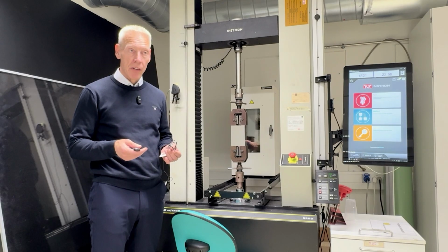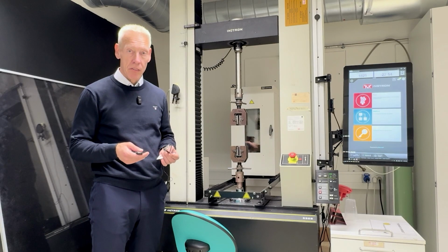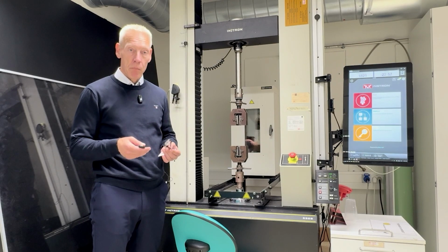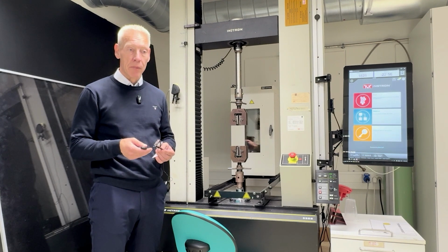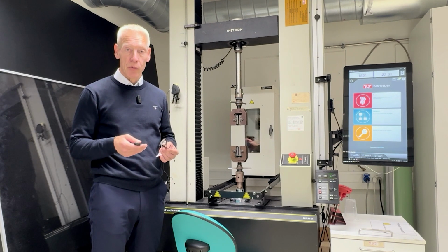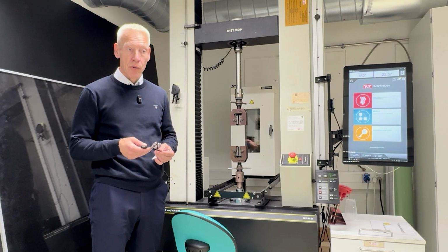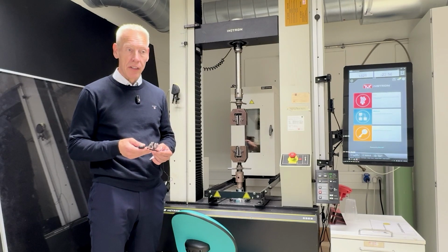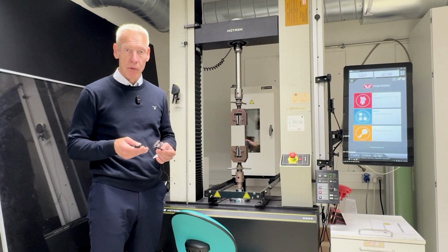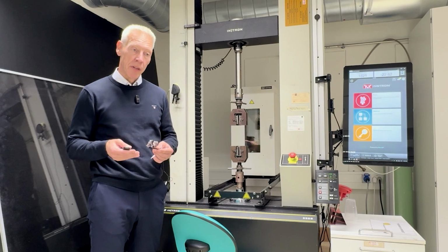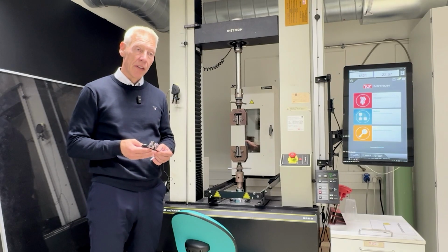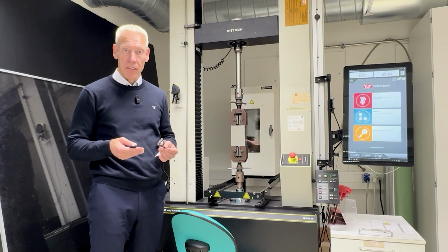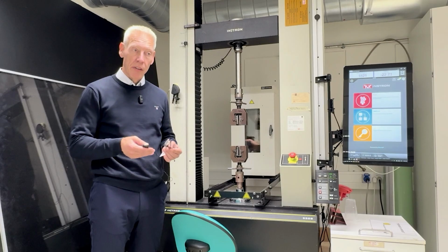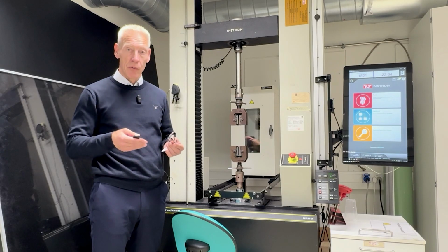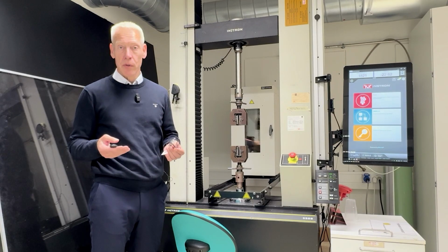If you do tests like relaxation and creep tests, it's very time consuming, but you measure something else in the material structure than you do in a short-term test. Viscoplasticity and the effect of time on materials are very, very dependent on the structure, and variation in crystalline size and so on you might not capture in a short-term test, but it would be very visible in a long-term creep test, for example.